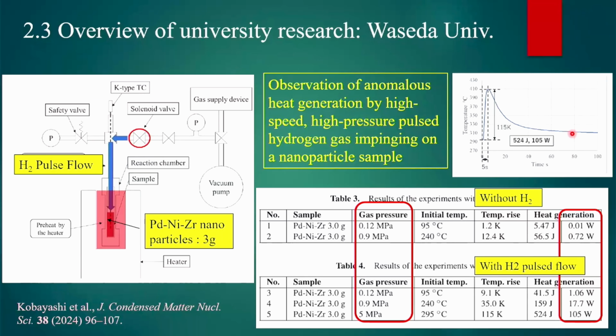And this one is a research activity by Waseda University, Professor Naito. And they use a similar sample: palladium, nickel, zirconia particles. They use a very high speed, high pressure hydrogen pulse, like a shock wave. And they detected the excess heat by the collision of a heat shock of hydrogen gas.